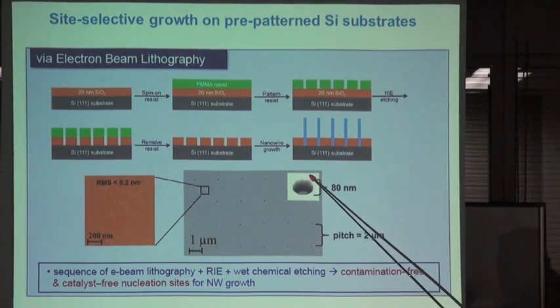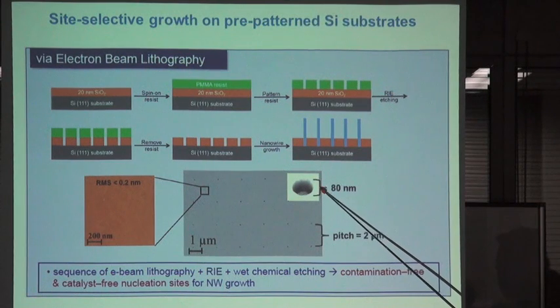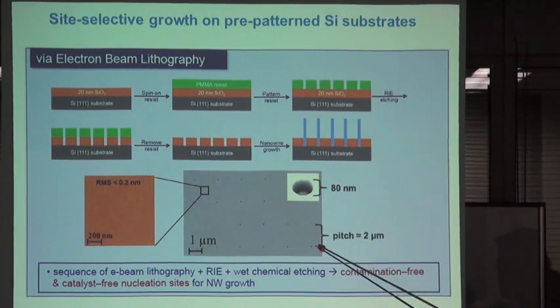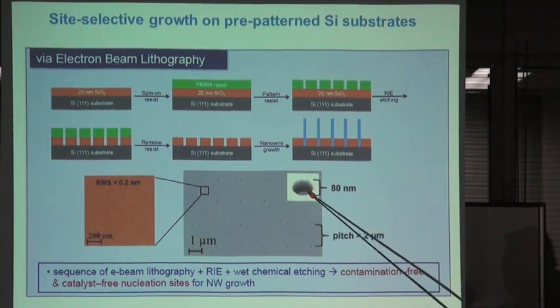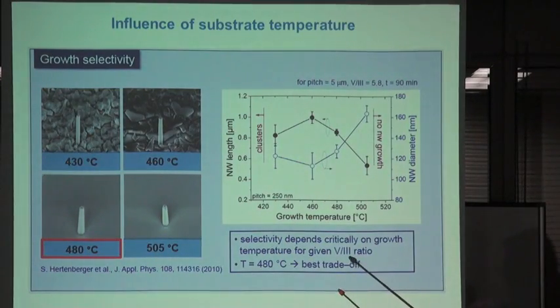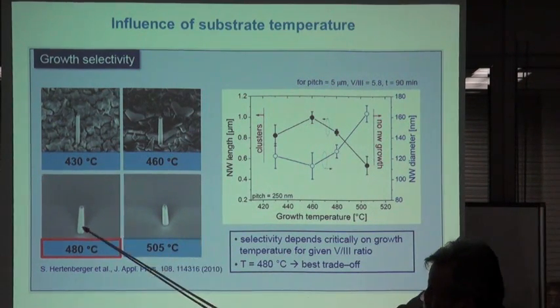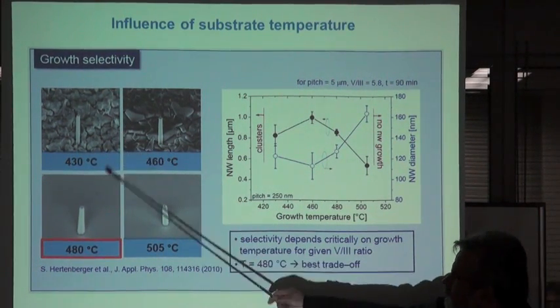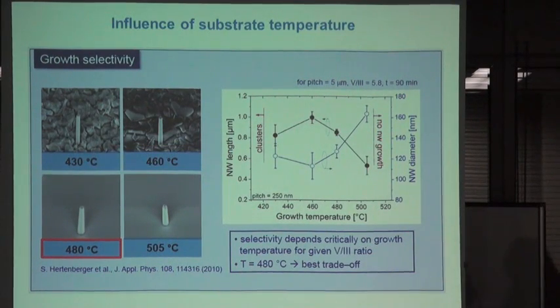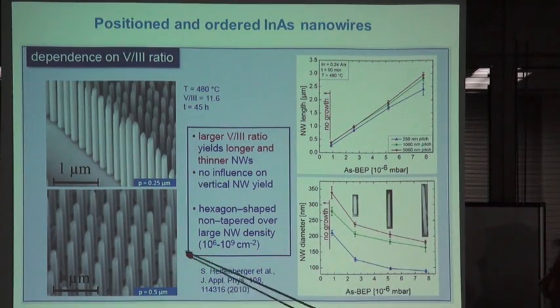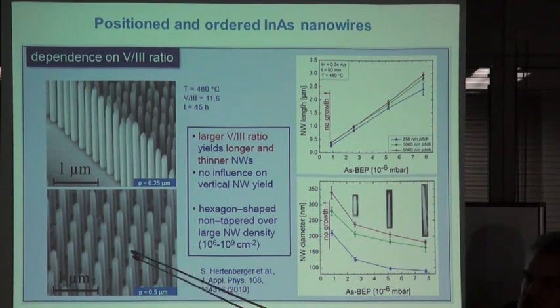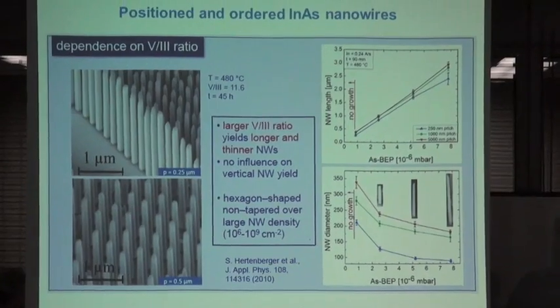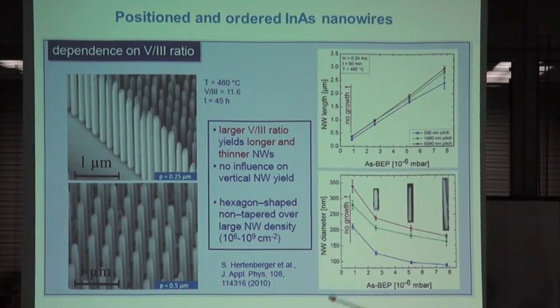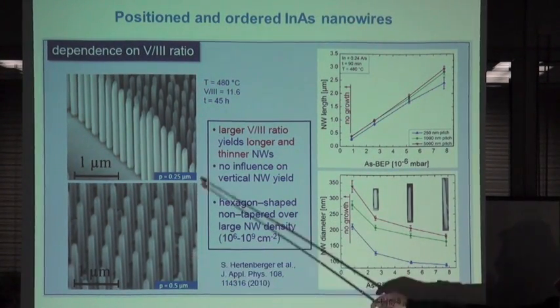And this is a hole shown enlarged. This is an 80 nanometer hole. We changed the pitch in a wide range and changed the diameter in a wide range, and looked at what we get. And actually, again, you see there's a certain temperature where this is optimum, in this case 480 centigrade on such a patterned substrate, and then you can get highly regular arrays with a yield which is more than 95% for indium arsenide. This is now indium arsenide on silicon.